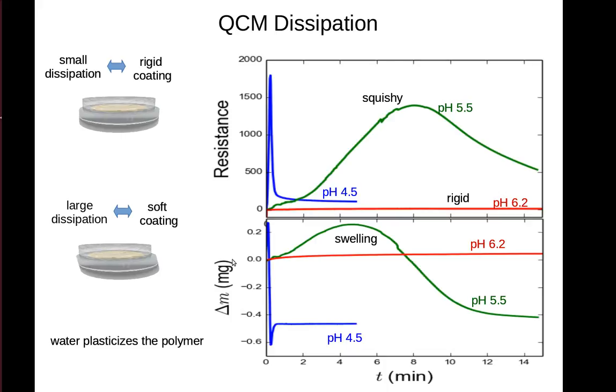Here are two plots comparing the mass versus time and the resistance versus time. Again, at 4.5 there's very fast dissolution, and at 6.2 very slow. The resistance shows a very similar effect.